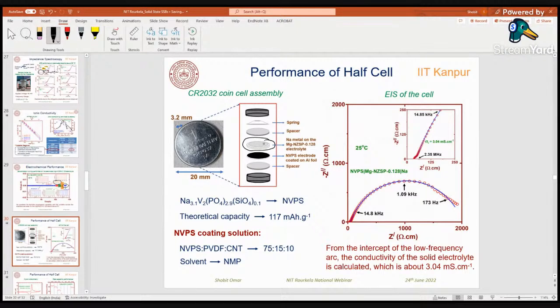We pressed the sodium metal over and spread the sodium metal on the ceramic pellet, and we use a coated NVPS cathode. To improve the interface between the solid electrolyte and the cathode, we add a few drops of liquid electrolyte. That will increase the sodium ion transfer from the solid electrolyte to the cathode.